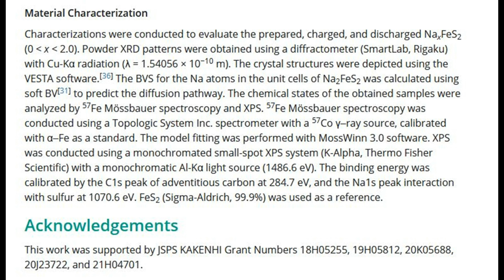57Fe Mössbauer spectroscopy was conducted using a spectrometer with a 57Co ray source, calibrated with Fe as a standard. The model fitting was performed with MossWinn 3.0 software. XPS was conducted using a monochromated micro-focused XPS system, K-Alpha, Thermo Fisher Scientific, with a monochromatic Al Kα light source, 1486.6 eV. The binding energy was calibrated by the C1s peak of adventitious carbon at 284.7 eV, and the Na1s peak interacting with sulfur at 1070.6 eV. FeS2, Sigma-Aldrich, 99.9%, was used as a reference.